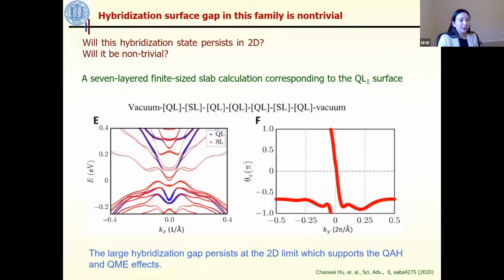So can this hybridization gap persist and support QAH in the 2D limit? Then Tyrone performed a DFT calculation on a 7-layer slab structure that has the QL1 termination on both surface sides. It turns out that this surface gap actually persists even inside this 7-layer slab structure. Furthermore, this gap is non-trivial, and it will still support the QAH and QME effect in the slab. So this result opens a new door for the material realization of QAH. That is, not only a Dirac gap can host the QAH, but also a hybridization gap from a Dirac band and a magnetic band may host the QAH too.